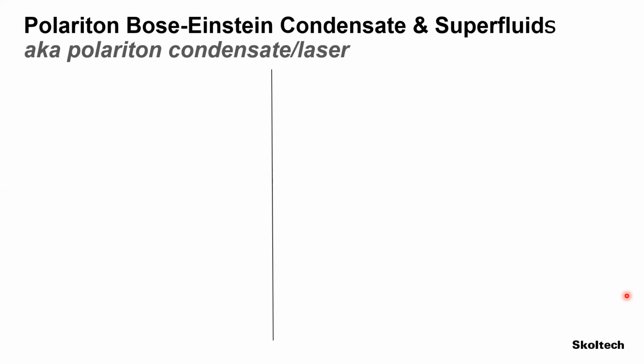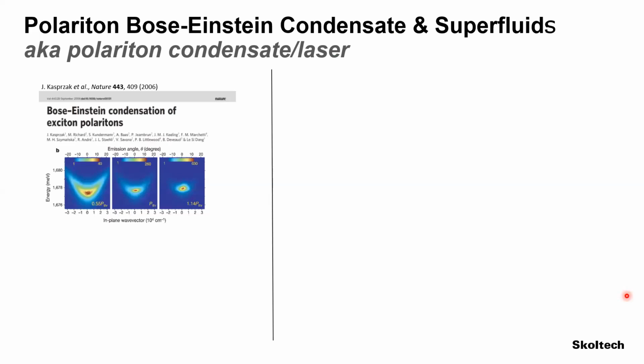Here you can see photoluminescence from the lower polariton dispersion. As you increase the density of polaritons in the system, you see that you go in the reciprocal space to condense into a state which has a macroscopic coherence. So the first demonstration of Bose-Einstein condensation was done at cryogenic temperatures.